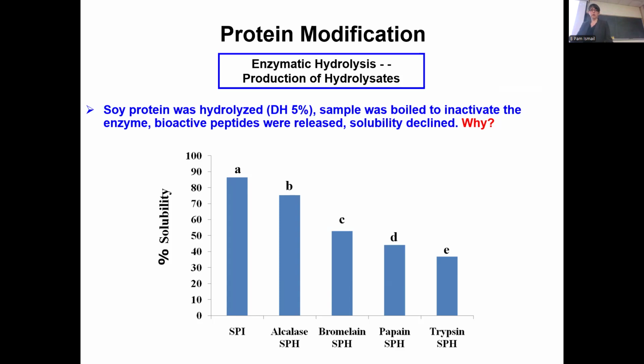Think of the theories we learned about. I don't understand. So you said the commercial sample is not soluble because it is hydrolyzed. No, the commercial sample that we usually get for SPI, we don't know if it's hydrolyzed, they don't tell us, but it went through processing, homogenization, trypsin inhibition, spray drying, the hexane extraction at the beginning to get the fat out. So it saw a lot of treatment. So it's denatured and it's not very soluble. But we wanted to control how we produce the SPI and control its treatment. So we produced it in the lab and hydrolyzed it. We thought that we were going to enhance its solubility, but it went down. Why?